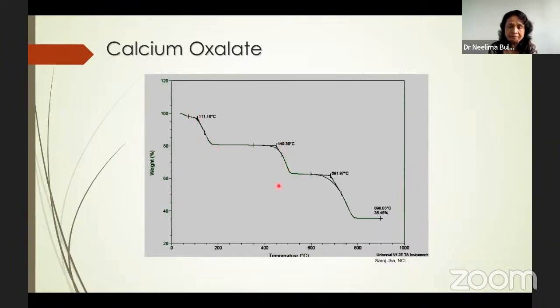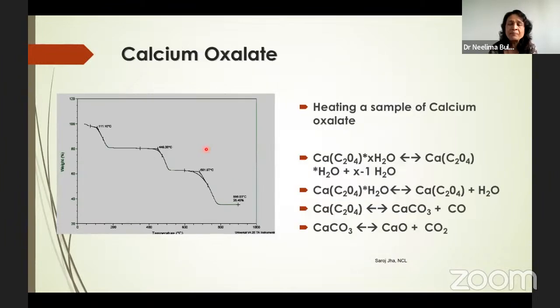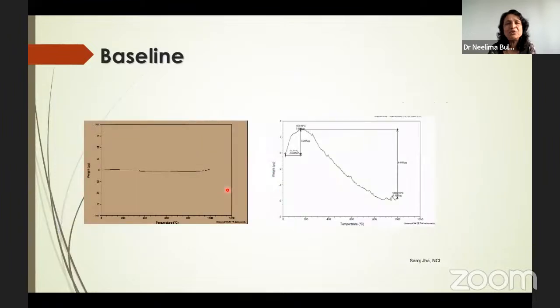And for mass calibration, there are materials like calcium oxalate, for which the weight changes or weight losses at particular temperatures are known as per their reactions. Like calcium oxalate, if you heat it, it forms calcium carbonate and water gets evaporated. You know how much water percentage gets evaporated, so you can exactly calibrate it and do the mass calibration also here. I will not spend much time on this because I know that most of you are doing this in your area.